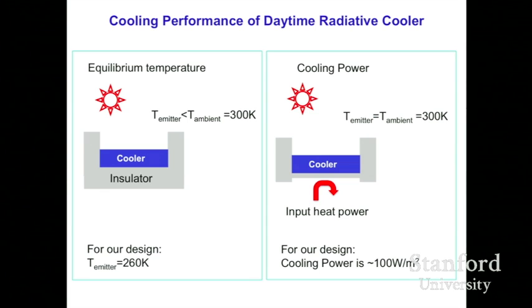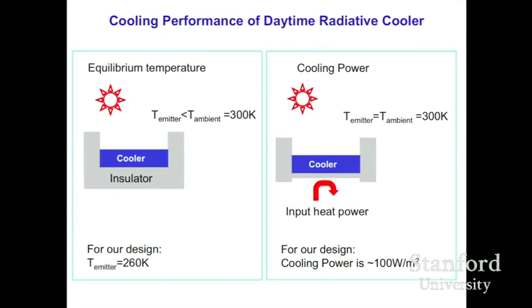Alternatively, since the cooler itself has a temperature below ambient, you can put a heat load on. And as you put a heat load on, its temperature is going to rise. And you can ask, well, how much heat can I actually put on the structure in order to bring its temperature back to the ambient? And it turned out that the power that you can put in, which therefore is a measure of how much cooling power you have, is on the order of 100 watt per meter square.